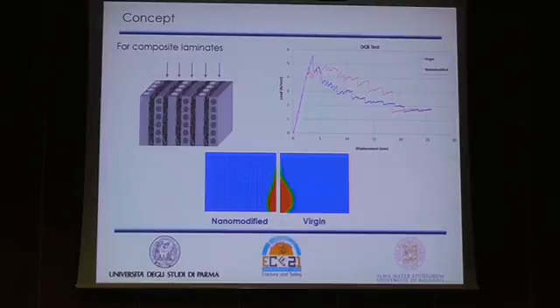In fact, in the past, many authors, including some of the current work, had already developed studies dealing with the possibility to substantially increase the energy dissipated by the laminations by using nanomats at the interfaces between the laminate layers. As you can see in the top right of the screen, there is a comparison between the load displacement curve obtained during a low velocity impact event in a virgin laminate and a nanomodified laminate, in which some nanomats were placed at the interfaces.